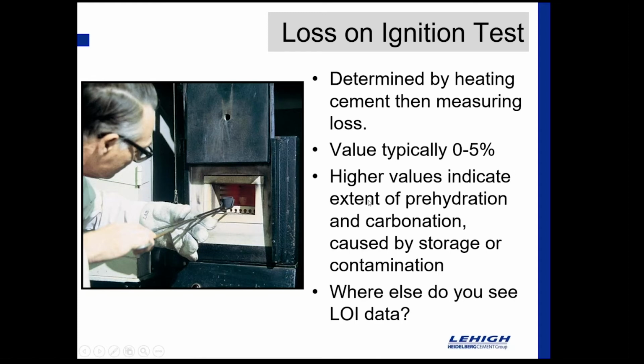Higher values indicate extent of prehydration and carbonation, and those can be caused by storage, could be caused by leaky storage. You might have a tanker truck that didn't have a lid snug down, or a rail car that doesn't seal properly, or maybe your silo has some kind of leaking system in it, or just overall contamination, maybe the tanker carried something before cement that would be causing you an issue. In terms of where else you might see LOI data, anyone that deals with ready mix and buys fly ash, you're looking at LOI data on that material as well. And we know higher LOI could be problematic.